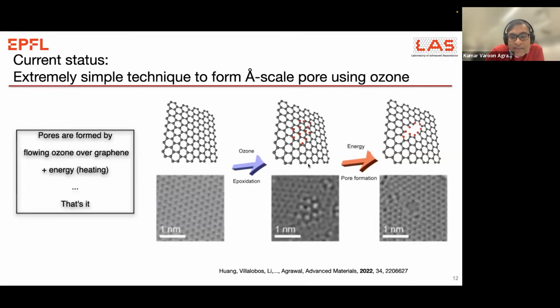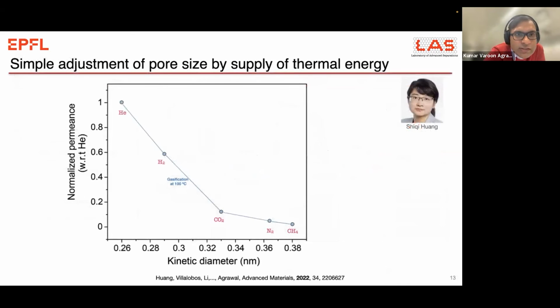All right. But at this stage, there are no holes, right? Once we provide energy to this, for example heating, then you can create holes, and depending on the amount of heat you give, you can tune the size of your hole. Just to give you an example of adjusting the pore size by heating, this particular coupon of porous graphene was made by heating at 100 degrees C.